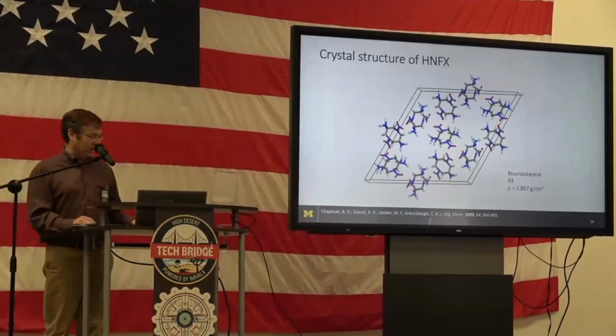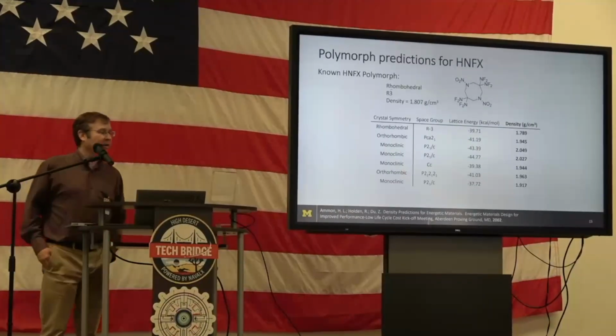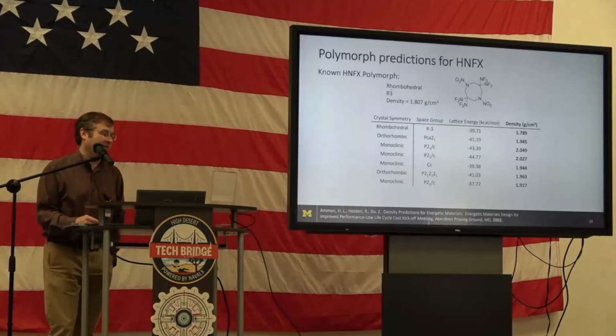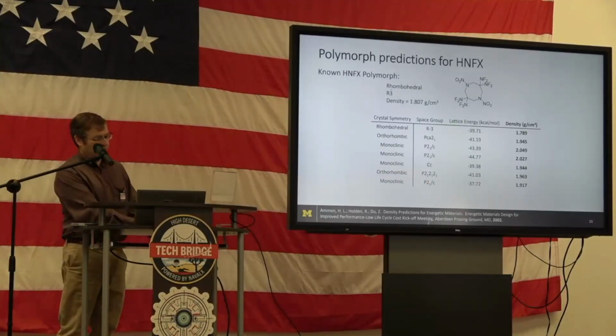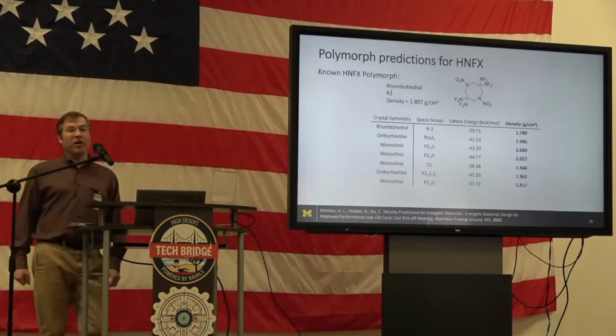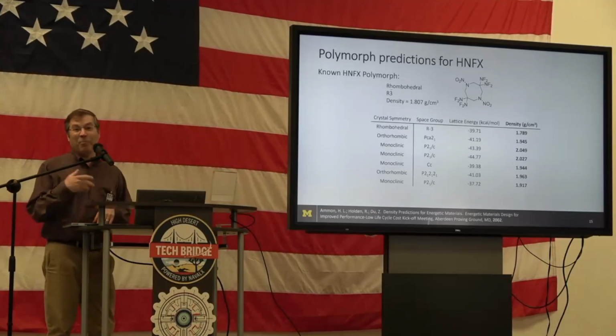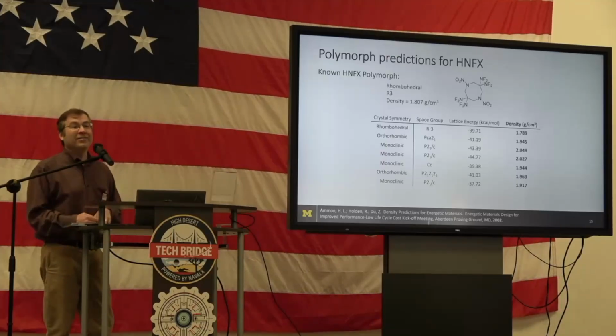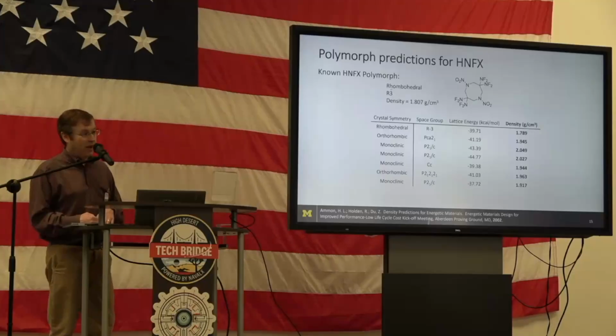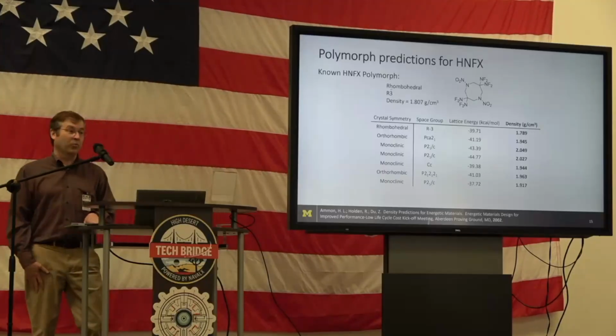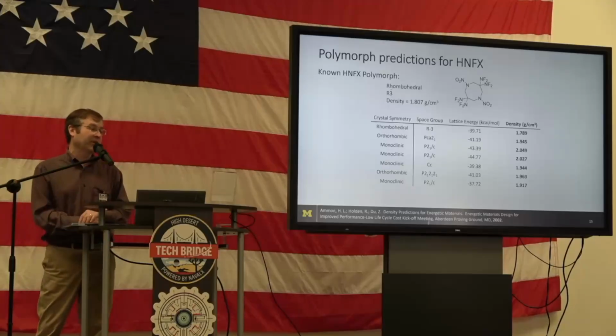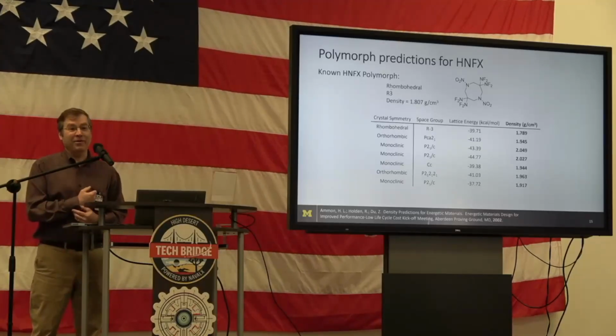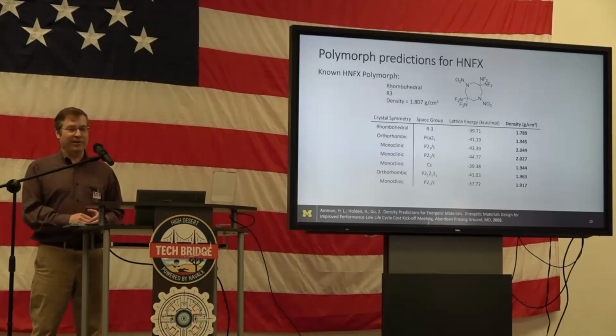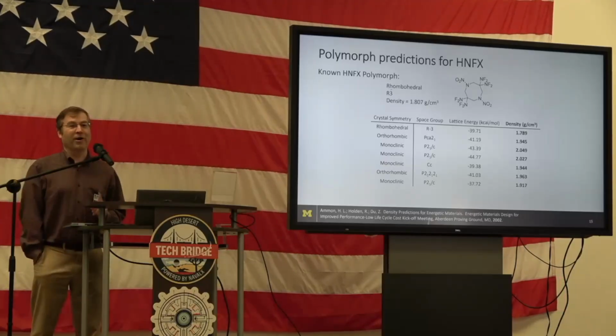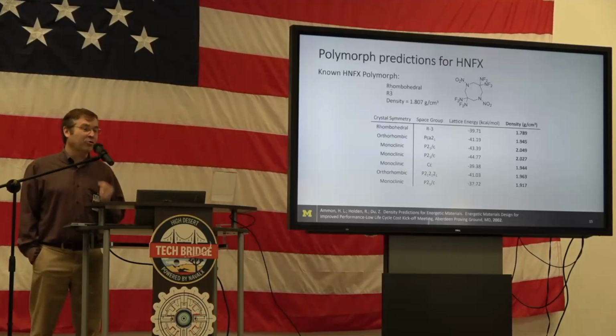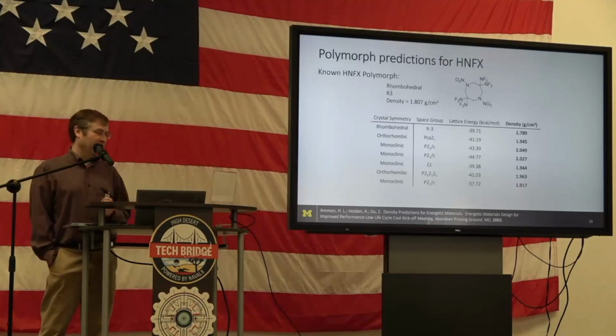So what is predicted? So here is the polymorph predictions for HNFX, and you can see this is basically the known one, and then there are a whole bunch of others that are predicted to have densities about 0.2 better. And not only that, they're predicted to be more stable, some of them. We were never able to get anything except that one polymorph of HNFX that has a density that is too low for it to be usable.